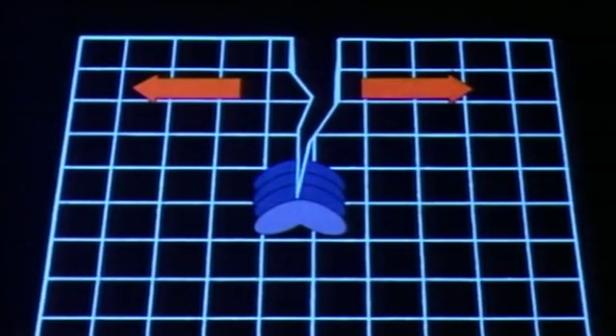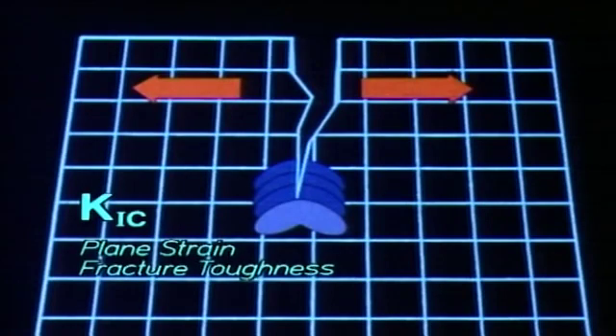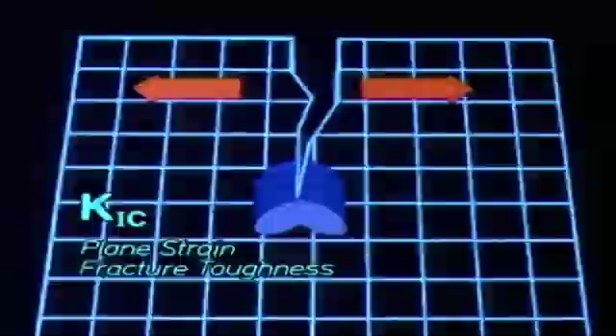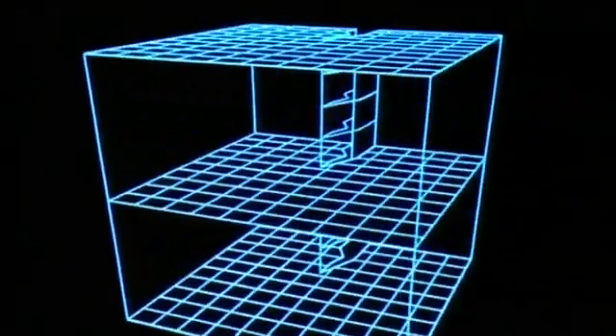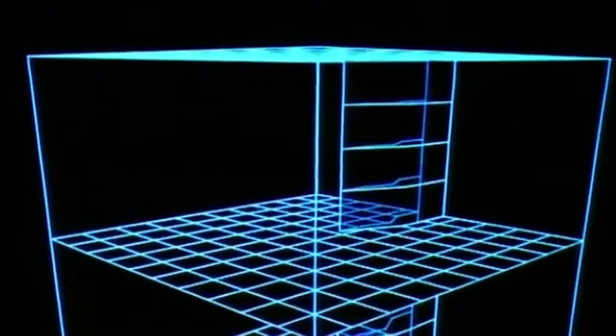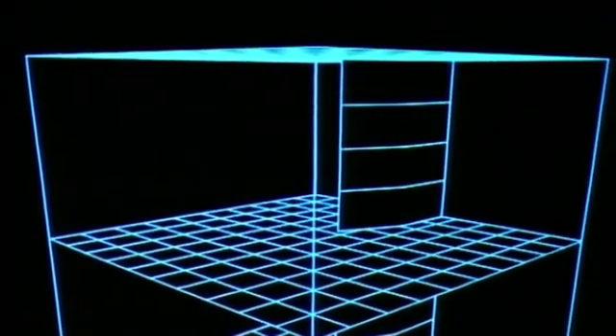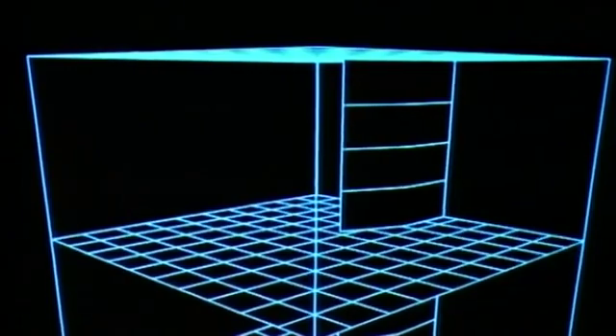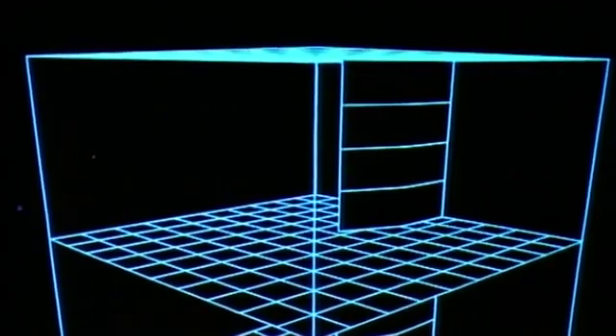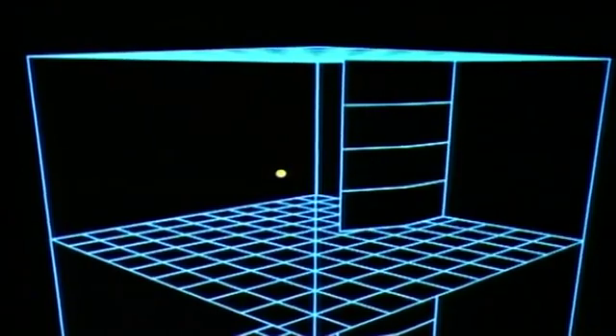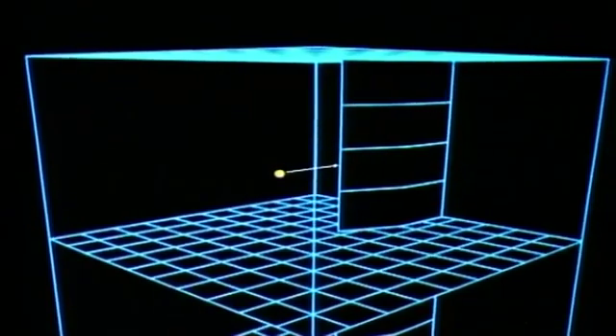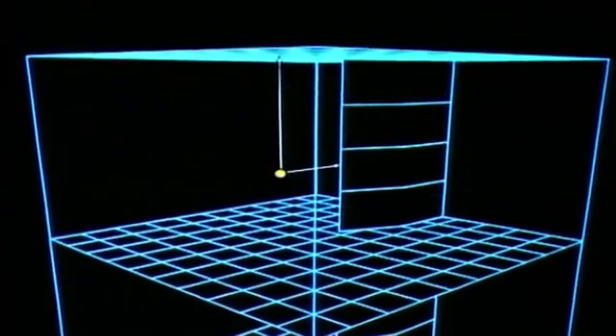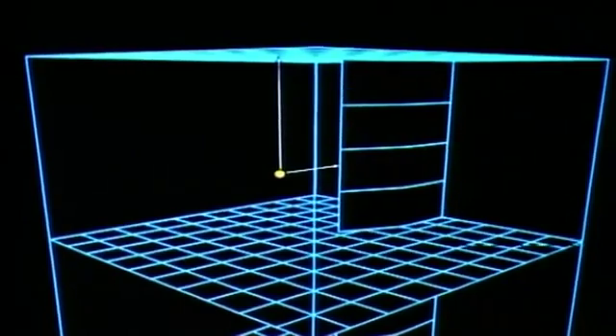Every material has its own characteristic value of plane strain fracture toughness, or K1C. But what exactly does the term plane strain mean? To show this, first let's imagine a purely brittle material with a crack in it. By definition, this material would deform only elastically, even right up to the crack tip. Let's consider a point near the centre of the specimen, a very small distance ahead of the crack tip. This point is close to the crack tip, but a long way, comparatively, from the edge of the specimen if the sample is reasonably thick.